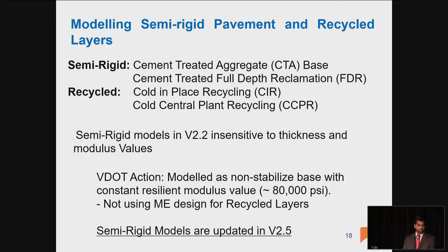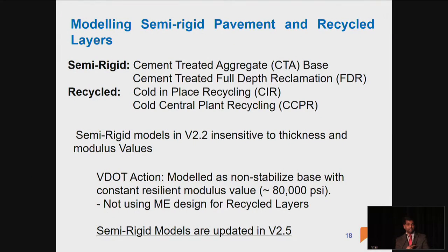The other thing is modeling semi-rigid pavement and recycled layers. Like I mentioned, we use a lot of cement-treated aggregate. Also, we use cement-treated full-depth reclamation. The version we are currently using is 2.2, and after this, there is one more version released. But version 2.2 is very insensitive to thickness and also the modulus values for semi-rigid pavement. If you input the CTA modulus or different thickness, it's very insensitive. So what we did is we modeled it as an aggregate base, but we use a high resilient modulus, 80,000 PSI, both for the cement-treated and FDR cases.